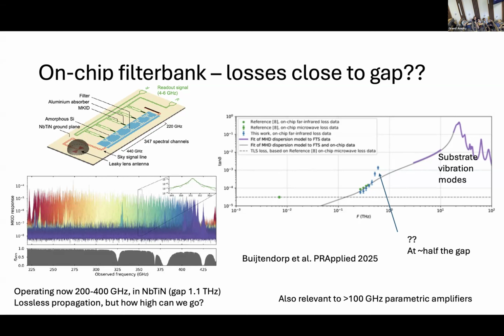So what you see here as context is the loss tangent of this stuff. And it's measured in this case in a Fabry-Perot geometry. So we make a Fabry-Perot resonator where this signal of hundreds of gigahertz can bounce around. And you detect it at the end of that Fabry-Perot resonator again with an MKID detector. But you really detect then what the losses at these 300 gigahertz type of frequencies are. And this is actually the data.